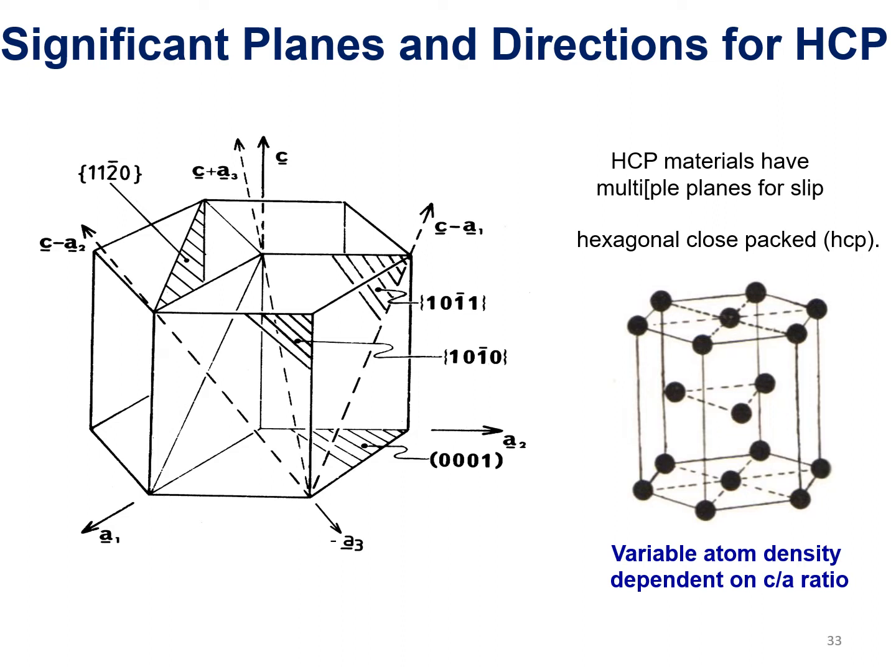The complication with the hexagonals is, if you can see here, this atom here, which is part of the 1-0 bar 1 plane, is actually not in the same plane as these atoms here that define the face of the prism. There's less corrugation for this plane, for what's called the pyramidal plane.